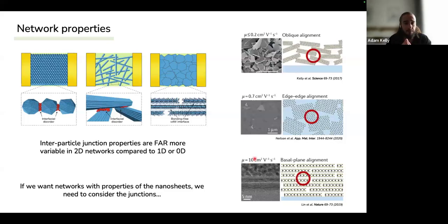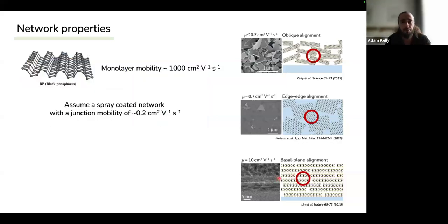So if we want networks with the properties of the nanosheets themselves, what we need to do is be very, very considerate about the junctions where they come into contact. So let me give you an example of why this is important, just very briefly. If we take a material like black phosphorus, this is a mobility of about 1,000. It's been theorized. But let's assume we have a material where the nanosheets have a mobility of 1,000, and the junction resistance gives us a network mobility of 0.2.